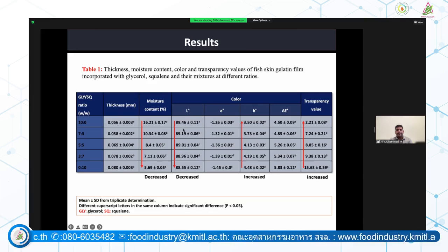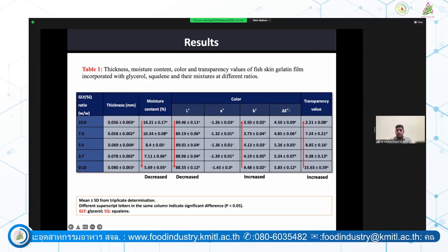And we can see the lightness. Again, this was contrary to what we would desire. Generally for the film packaging industry, we need films with higher lightness value, but with the addition of squalene, we found a little decrease in lightness value, but not to a significant level. And next we can see the transparency. Transparency was higher for the glycerol added films, and lower in the squalene added films.